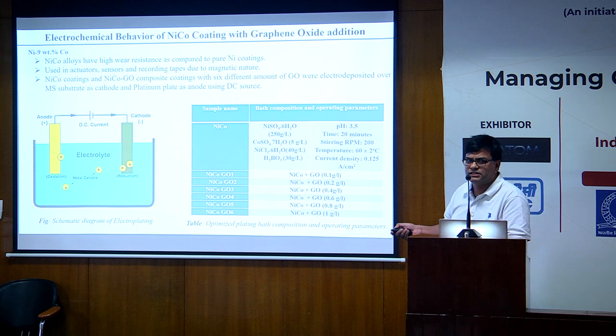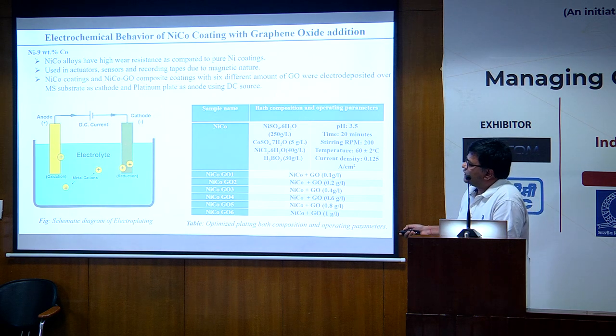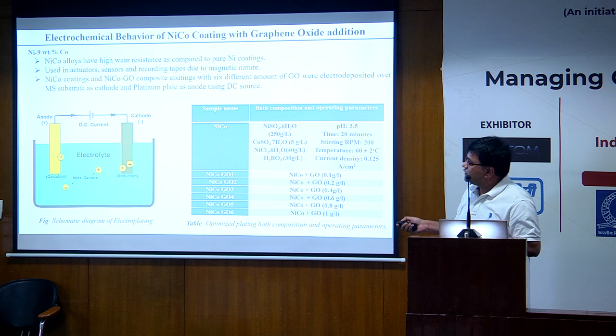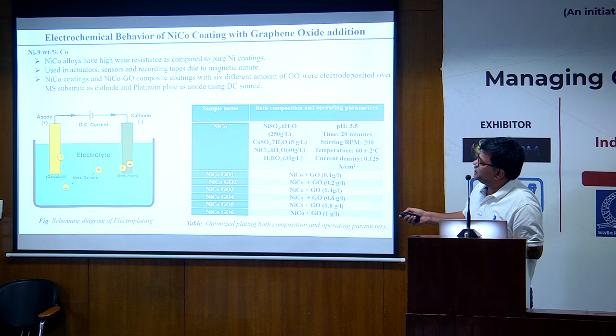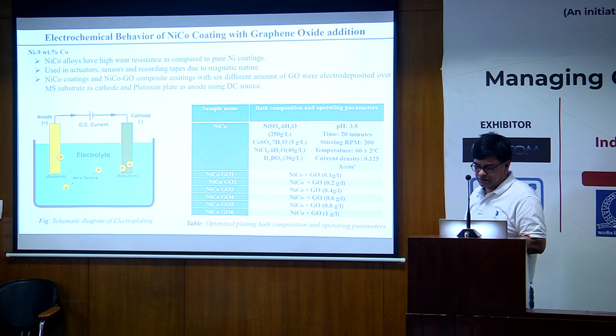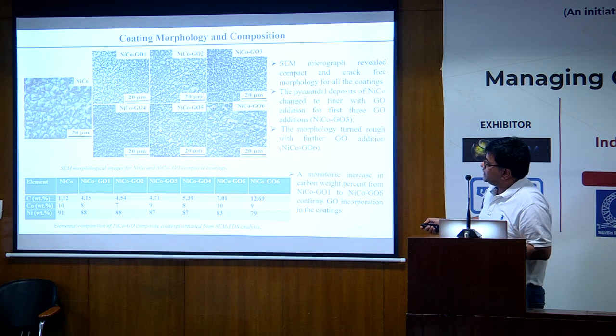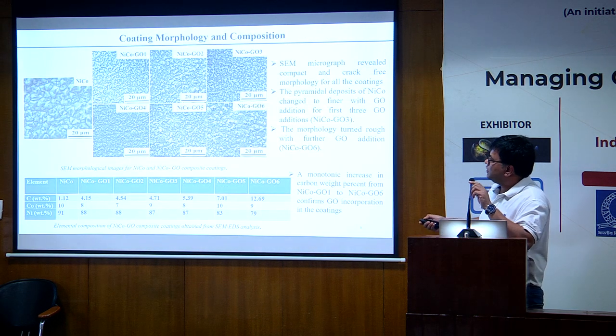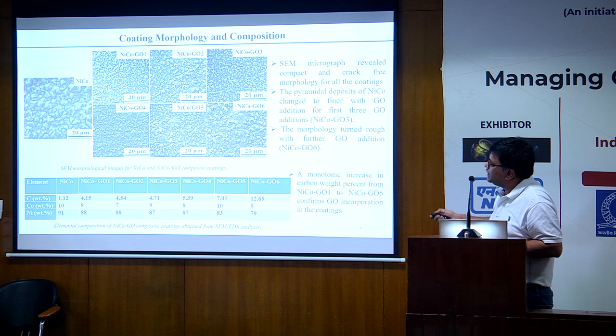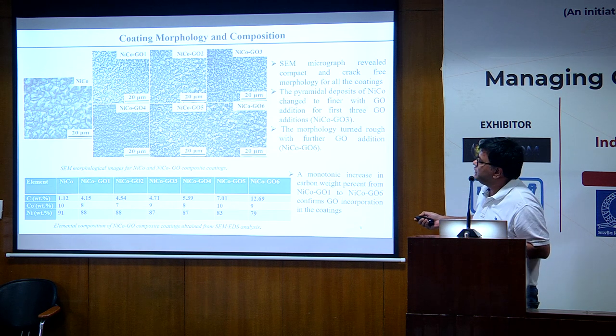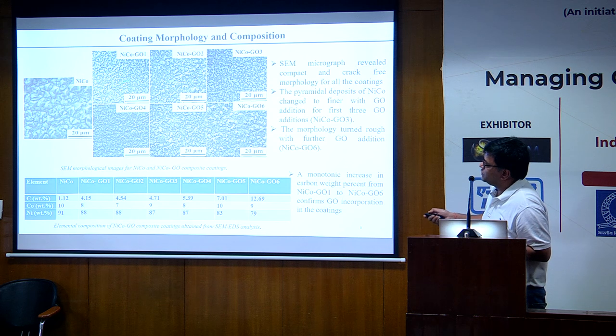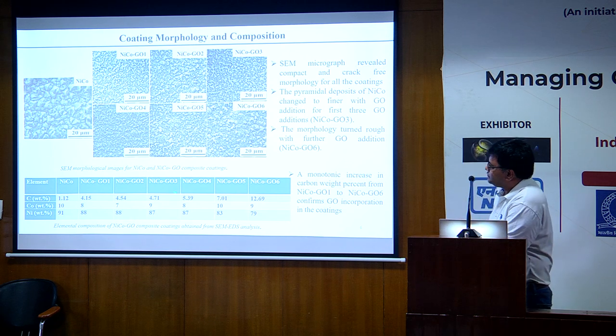So this is a very traditional method where you use an anode and cathode and an electrolyte, and this is the bath chemistry. And the coating that I'm going to talk to you about here is about 9% cobalt, so nickel with 9% weight cobalt. And these are the images of the coating. You can see that all these coatings are nearly compact coatings. They do not have any major cracks or something, and the morphology also remains almost nearly similar.